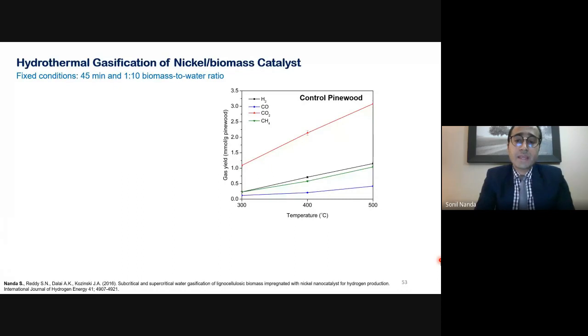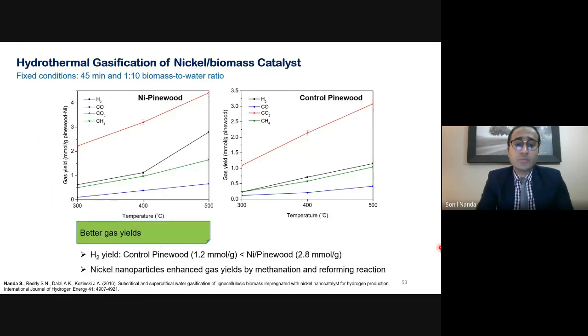Now, after we determined that, we also did a hydrothermal gasification, supercritical water gasification of the two feedstocks. And what we determined here, I'm showing you only for the pine wood, you can see this is the control pine wood and the nickel impregnated pine wood. You can easily see that the yield of hydrogen in the nickel impregnated pine wood increased drastically when compared to that of control pine wood.